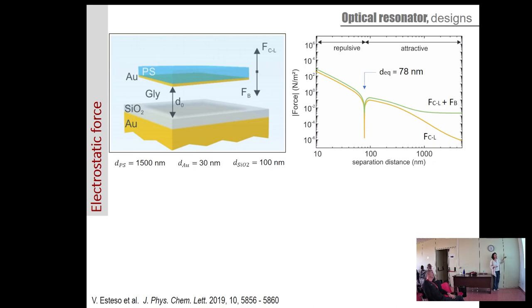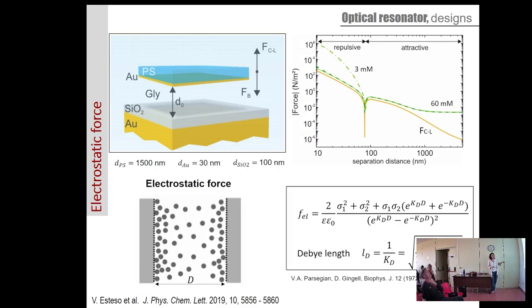And these two curves correspond just to the Casimir force, and also when we included gravity and buoyancy. We also analyzed the possible effect of having electrostatic forces, and we evaluated through the Poisson-Boltzmann methodology the effect of including monovalent salts. Whenever we have a low concentration, we have an additional repulsive component, but when we increase the concentration, then we really cancel any electrostatic component. So from now on, we are just going to assume that we are including enough salt in our glycerol. The optical properties are not going to be modified, and this is the analysis we did for that.